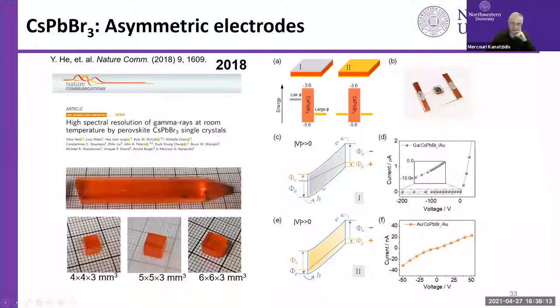So then we realized, let's make a device that addresses this. This is the energy diagram shown here. This is gold and gold on both sides. And this is the energy of the valence band and the energy of the conduction band. So you see we have a small energy barrier on this side, but a big energy barrier on that side. So then we changed one side and put a lower work function metal like gallium, where the energy of the gallium work function is here, and we have this asymmetric electrode. So when we bias this one way, both of the barriers are small and we get very high current. We call this the forward direction. But when we bias it the other way, both barriers are high.